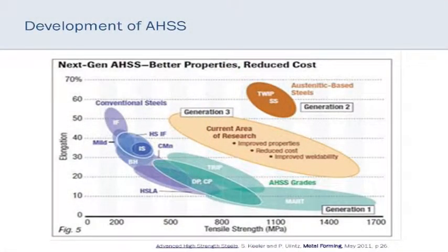And then this is our famous banana chart, where the material on the left is very formable. That's the IFs, like I talked about, in the 1980s, provided you with the ability to form it. But as we've grown to the high-strength low alloys and to the martensitic, we get very strong, but not as formable. But these advanced high-strength steels, the dual phase, are aiming up for that upper right-hand corner to help with formability and strength. And we've got some research being done with